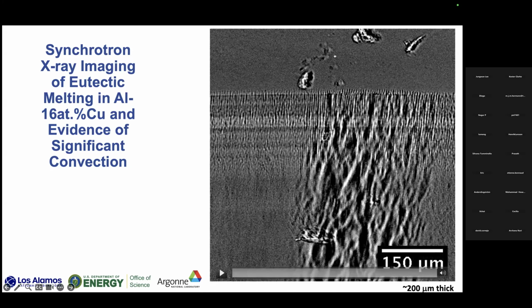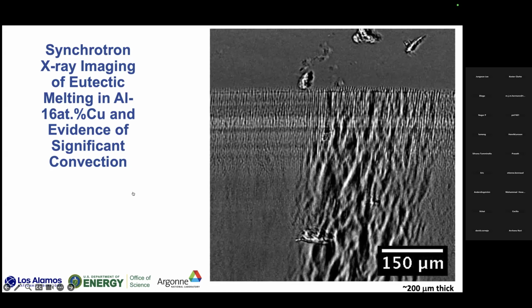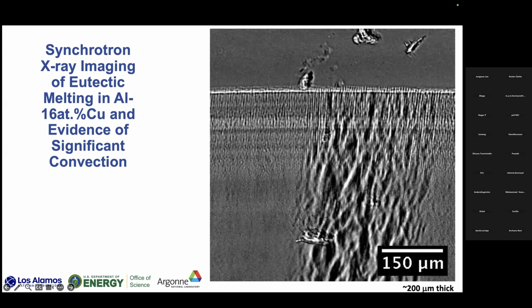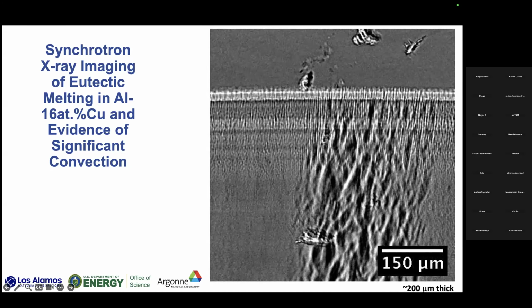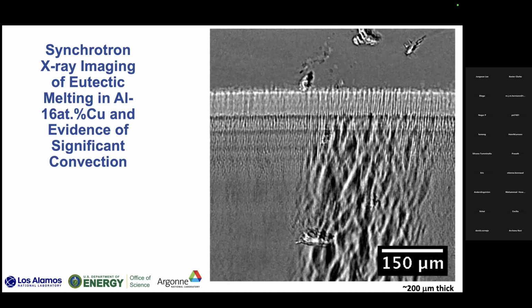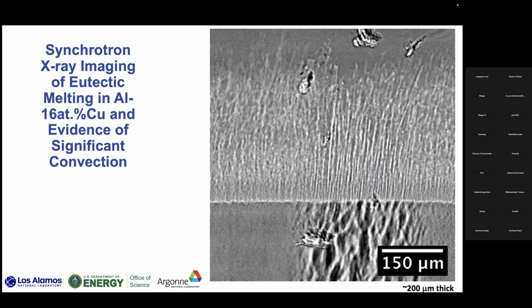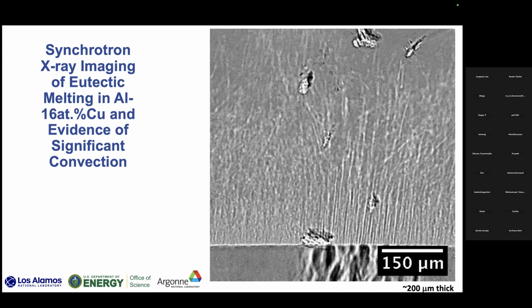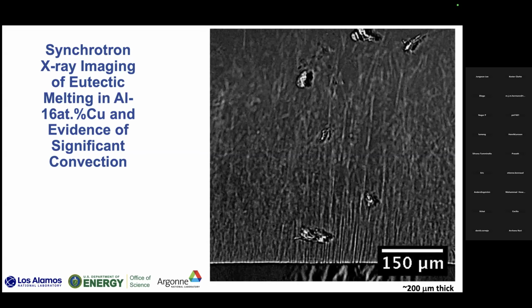I'm going to show you a top-down directional melt, and you'll see some interesting dynamics. On the melt, you see the breakup of the eutectic structure. You see the aluminum-rich phase float off into these matchstick kinds of fragments. And you certainly see things like convection happening in the melt.